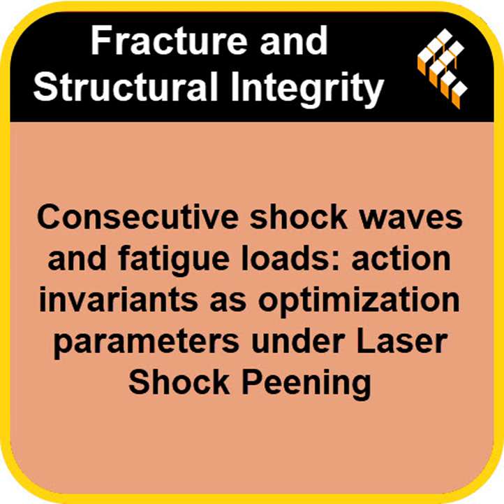Maximize the lifetime by choosing the optimal hit. Exactly. You're leveraging that fundamental link, that self-similarity reflected in the power laws, to design the most effective treatment based on physics, not just empirical correlation. So we started by looking at how to make aircraft parts last longer, went through shock physics, fractal dimensions, explosive impacts, and landed on this idea that a deep concept from physics, the action invariant, is key. It connects the initial shock treatment to how tiny cracks behave billions of cycles later, potentially better than our old engineering metrics.